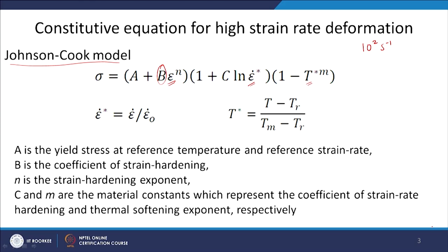One of the important ideas which you should understand here is that when we do any high strain rate deformation, whether in hot working or in this case even higher strain rate, more than 10 to the power 2, there is always a temperature rise in the material. When we are deforming the material, we are inputting energy into the material. Some of the energy goes into the deformation process, that means plastic deformation, and some energy goes in the form of heat, so there will be heat generation whenever you do a deformation.